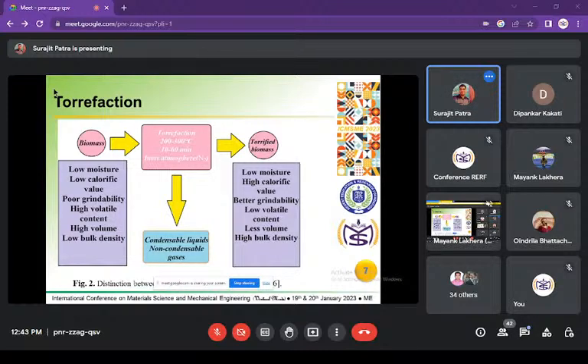Torrefaction is a controlled process in which biomass is heated in the temperature range of 200 to 300 degrees centigrade in an oxygen-free environment, or with a small amount of oxygen, to carry out our experiment. To provide a non-oxidizing atmosphere, nitrogen is the most commonly used carrier gas. The thermal method below 200 is used for wood preservation, while the higher temperature torrefaction method is used for energy purposes.